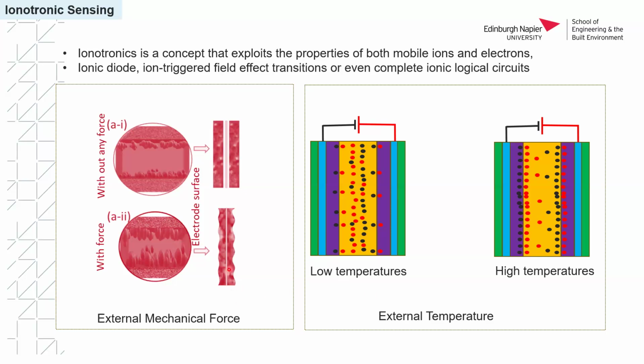In another case, when we have such an active electrolyte, there are plenty of ions. Depending on the type of potential you are applying, these ions will be adsorbed, diffused or absorbed into the surface. But when the external temperature or the temperature of the atmosphere is varying, of course, the packaging influences the temperature diffusion inside the material. We noticed that with the temperature variation, more orientation of these ions occurs, and that leads to changes in the energy density or the specific capacitance of the material.